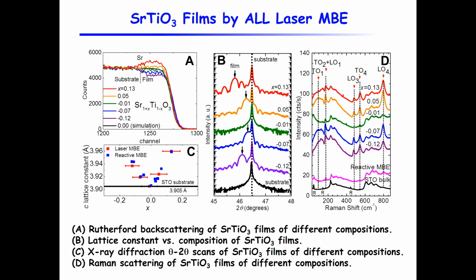And strontium titanate is a prototypical system that you can use for this technique. We've grown films, for example, with different stoichiometry. And from the RBS, we can measure the stoichiometry and compare that to what we designed it to be. And here it shows the c lattice constant as a function of the composition. It is known in the field that if strontium titanate stoichiometry is off from one-to-one, you will see the expansion of the unit cell. And here I show the result from laser MBE and the reactive MBE from Darrell Schlom's lab. And we found that the two techniques gave very similar results.